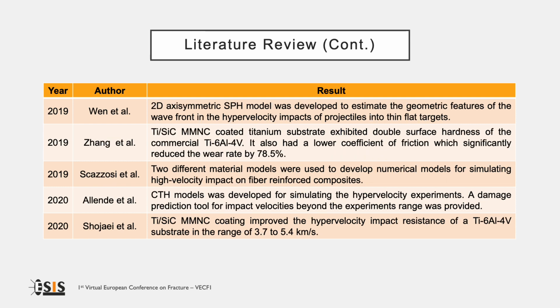Zhang et al. found that titanium silicon carbide metal matrix nanocomposite coating exhibited double hardness with respect to the titanium 6-4 substrate and decreased the friction coefficient. Consequently, wear rate was reduced by 78%. The authors themselves performed hypervelocity impact tests on coated titanium 6-4 and found improved impact resistance.